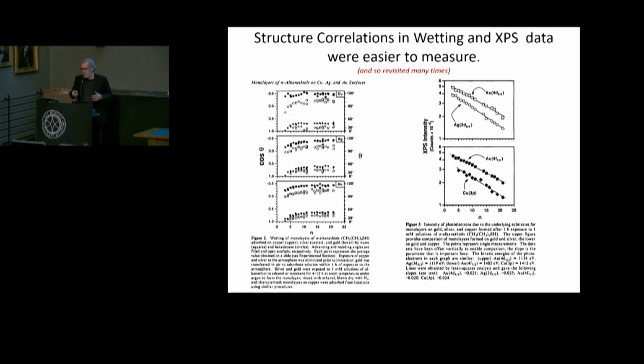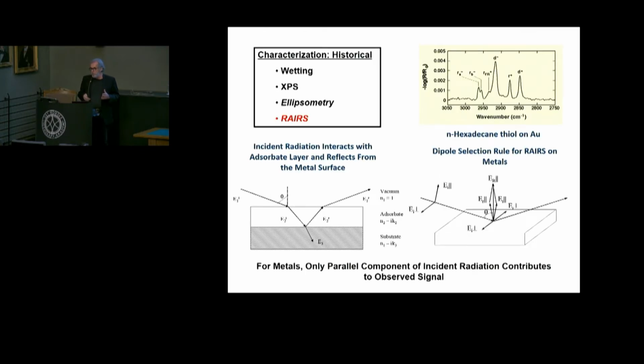And you see a characteristic scaling, for example, of core level data that shows that the photoelectrons associated with the metal substrate are being attenuated. And from that, you can get an idea of what the thickness is of the layer that's present. So the contact angle data is showing that this is a very coherent organic monolayer, and because it's oleophobic against the hydrocarbon, not wetting a hydrocarbon, it says that it's a very special organization. And that's actually a really important clue. And of course, from the XPS data, you get an idea related to coverage. But we really wanted more than that.